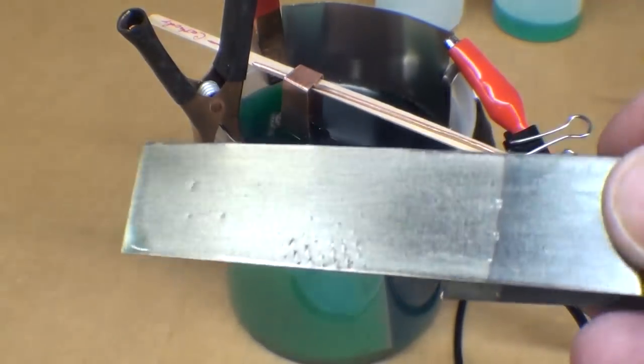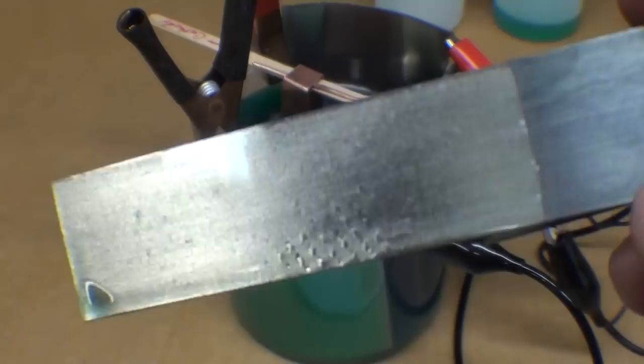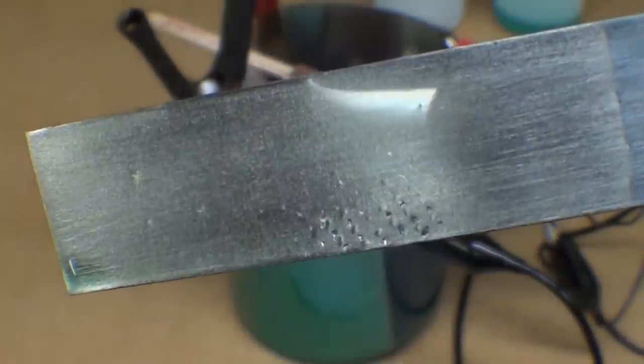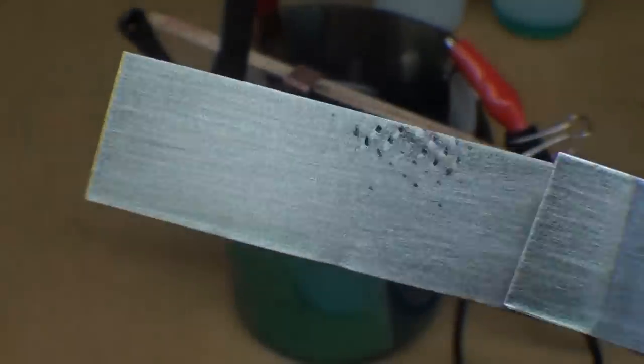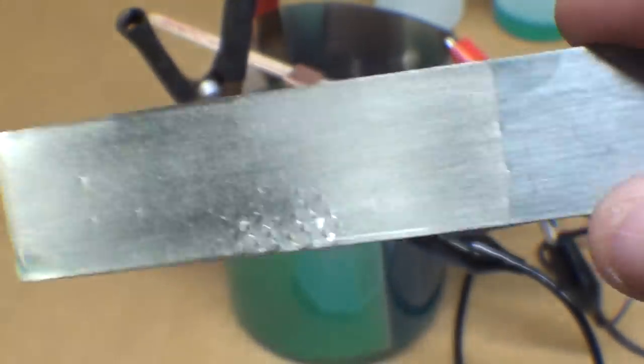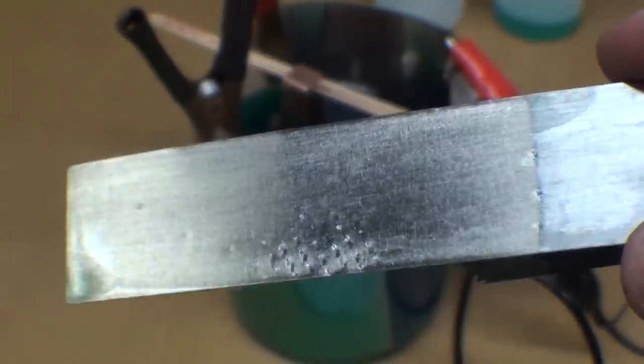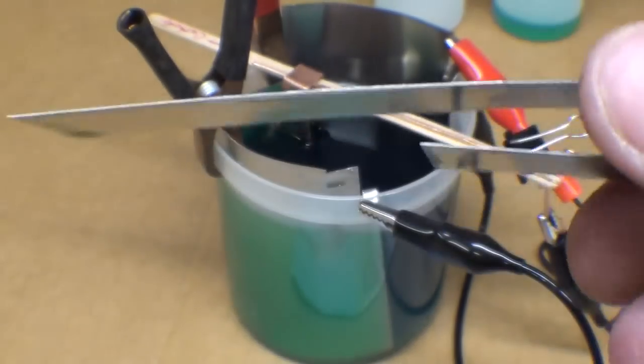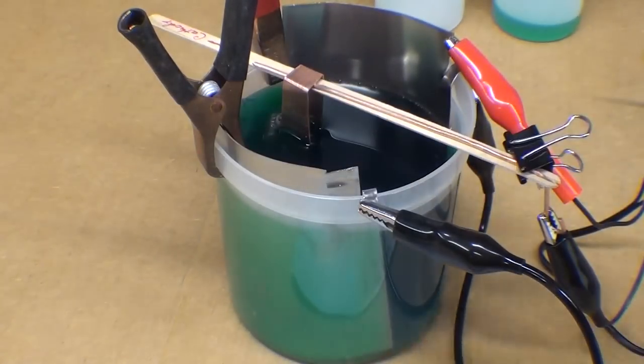I know it's hard to see that on the videotape. Remember also that the anodes are being consumed and eventually would be gone. It says in the directions that the metal is being deposited onto the work—the cathode—at a rate of one one-thousandth of an inch per hour with that voltage.